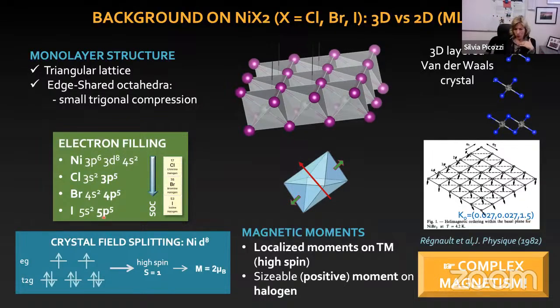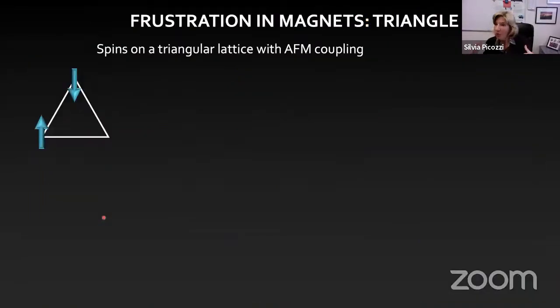And so these materials were studied in bulk form back in the 80s, and already at that time, by neutron scattering I believe, some complex magnetism was detected. And so one of the questions is, is this complex ordering kept when I move to the monolayer? And so this is why we basically started the analysis of a monolayer of nickel halide.